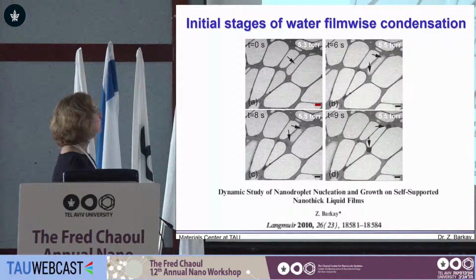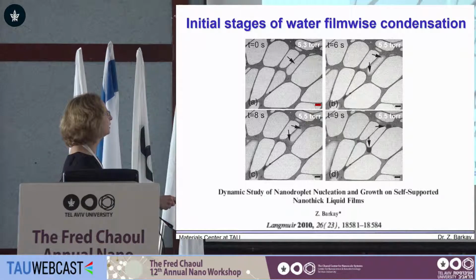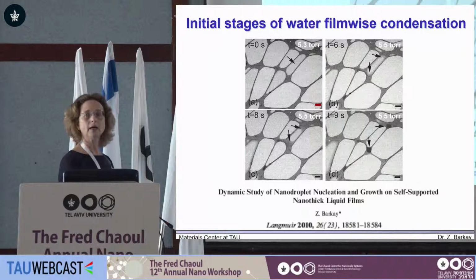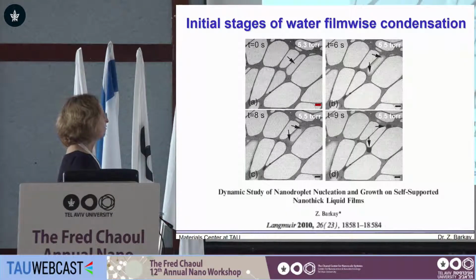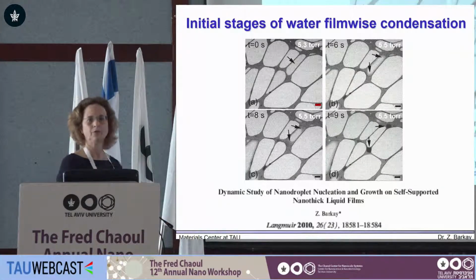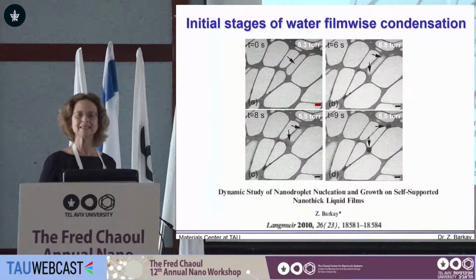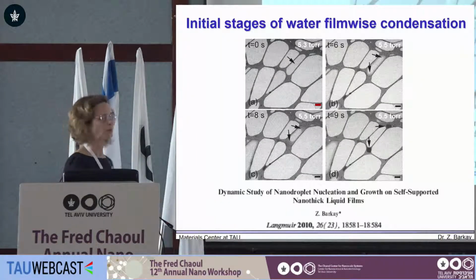These are initial stages of filmwise condensation. We have here the film, the liquid films, very thin liquid films. We can see that by elevating pressure, we can form condensation, which starts from outside in. You see this darkening of the area around, and it can continue under equilibrium even, giving a thicker film and a wider film. Finally, this film can result in some instability and break into droplets.